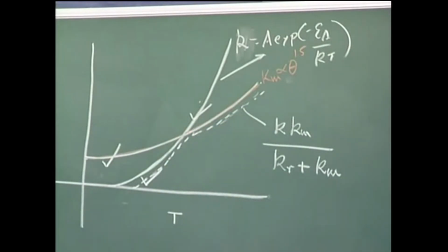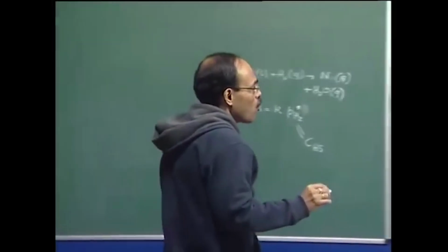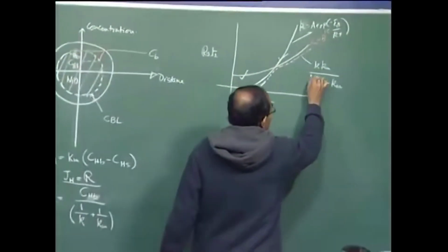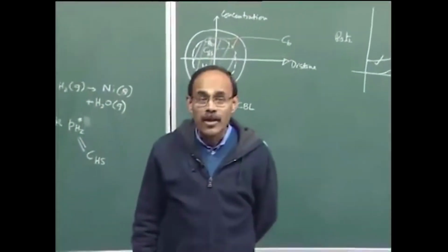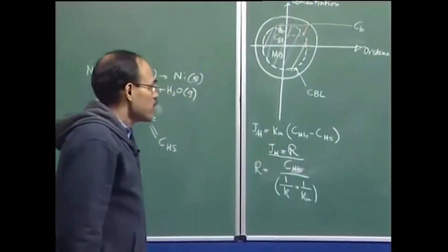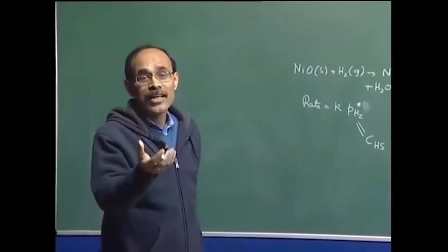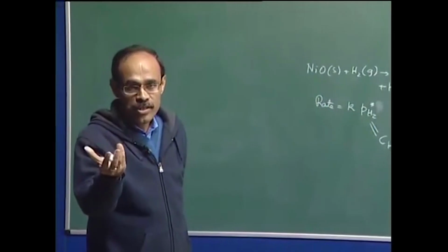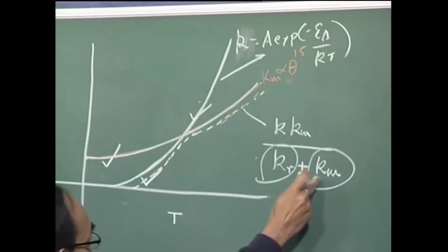So therefore, it is mass transport control, and the equation boils down to this. Now we can also, on the basis of this, find out the value of this, and then you can conclude which is the rate limiting step. So whichever step is going to show the largest resistance controls the rate, and these are direct measures of the resistances to mass flow.